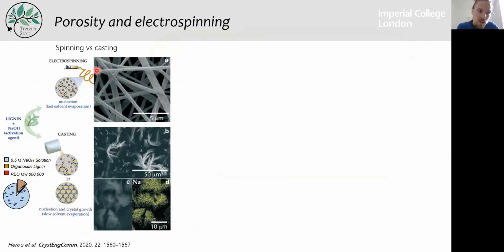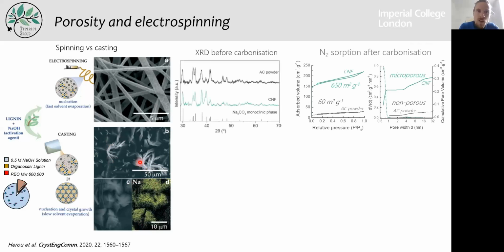And when we take this solution and we don't electrospin it, but just cast it onto a standard glass plate, as is usually done for standard activation procedures, we observe that these crystals are actually massive. They are micro-sized, and this is the EDS picture showing the presence of sodium in the salt crystals. So we've analyzed